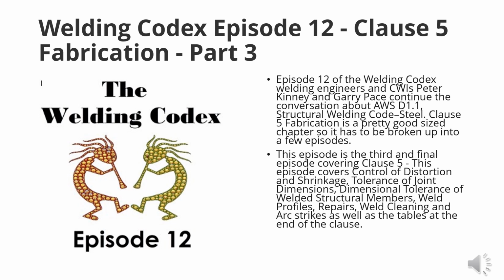And you're right, the one thing you have to watch out for is stacking of indications, where if your starts are always on top of one another, well, each little bit wasn't bad by itself, but all of a sudden you got 10 of them on there. Now you got a big lob of porosity. So they're simple little things. They make life easy. Highly recommend them.